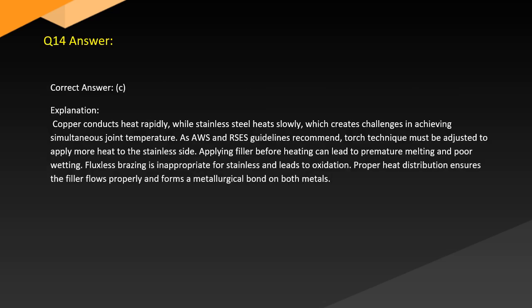Answer. Correct answer. C. Explanation. Copper conducts heat rapidly while stainless steel heats slowly, which creates challenges in achieving simultaneous joint temperature, as AWS and RSES guidelines recommend. Torch technique must be adjusted to apply more heat to the stainless side. Applying filler before heating can lead to premature melting and poor wetting. Fluxless brazing is inappropriate for stainless and leads to oxidation. Proper distribution ensures the filler flows properly and forms a metallurgical bond on both metals.